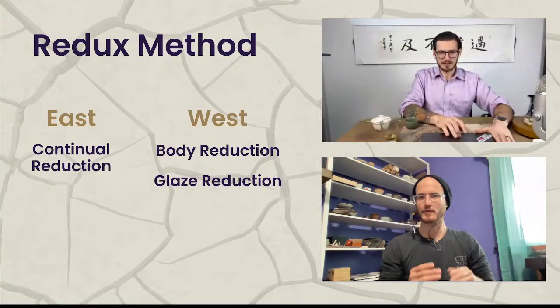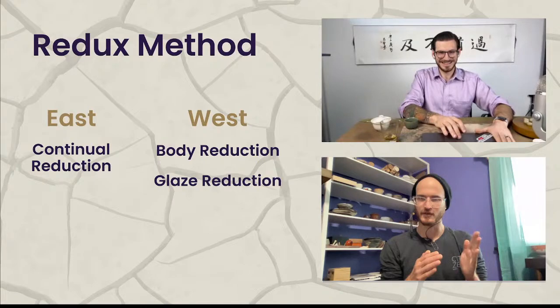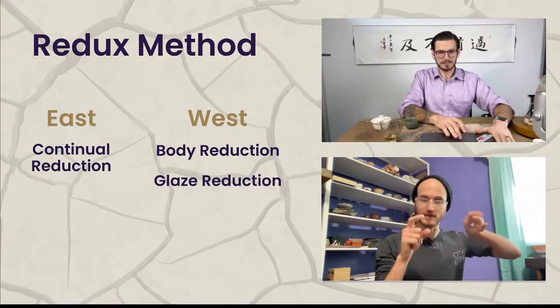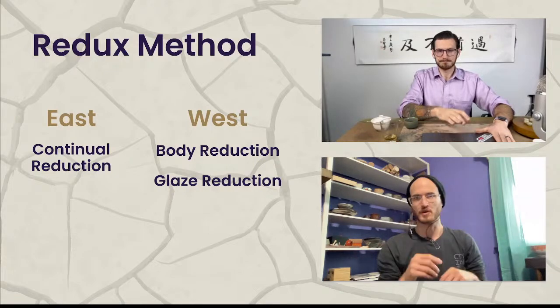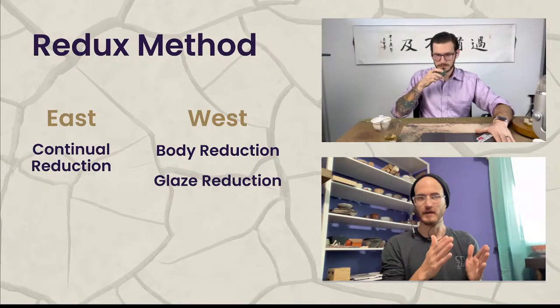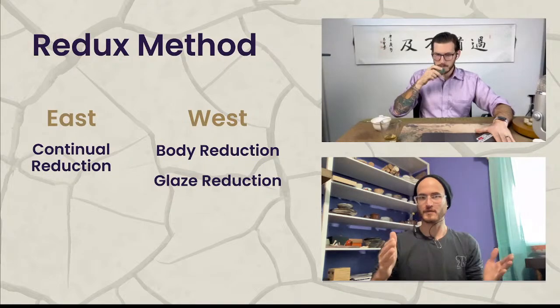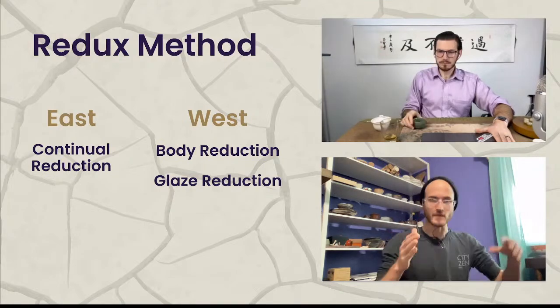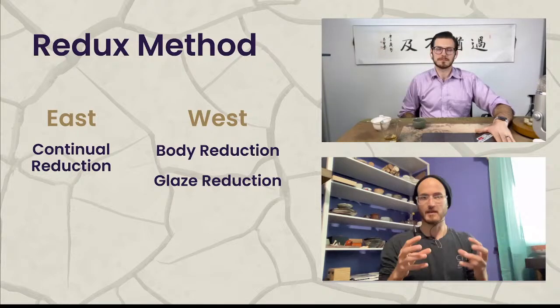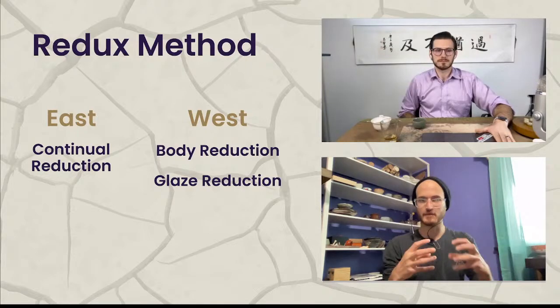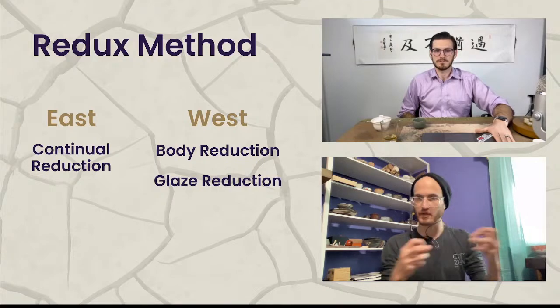So if you want to learn about ceramics, switch to Celsius on that. But from 900 C to 1000 C, or with pyrometric cones, which are temperature gauges inside of the kiln that bend at certain temperatures, it's cone 06 to 04. You'll put the kiln into reduction. So you'll close the damper and add more fuel and make sure that the environment inside the kiln is very turbulent and smoky and full of fuel so that it's pulling away the oxygen molecules from the clay.